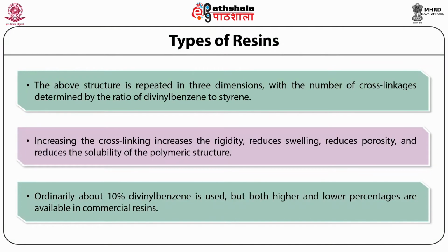Ordinarily, about 10% divinyl benzene is used, but both higher and lower percentages are available in commercial resins. The particle size of the product is determined largely by the extent of mechanical agitation during the reaction, so that resin beads of numerous grades sizes are available.